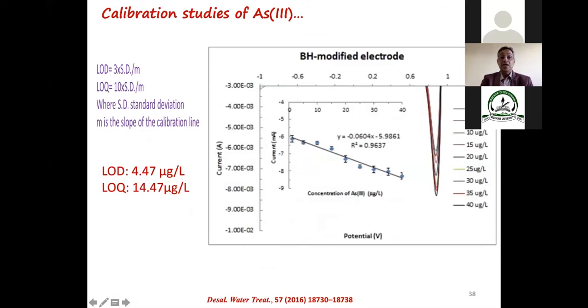And here is the calibration line that we obtained. We increased the concentration of arsenic 3 from 1 microgram per liter, or 1 ppb, to 40 ppb, and we get a good correlation line. Based on this, the LOD, limit of detection, which is 3 times the background signal, is around 4.47. As I initially mentioned, the EPA limit is 10 ppb, but now we are getting 4.47. This detection limit is much lower than the permissible level of arsenic.